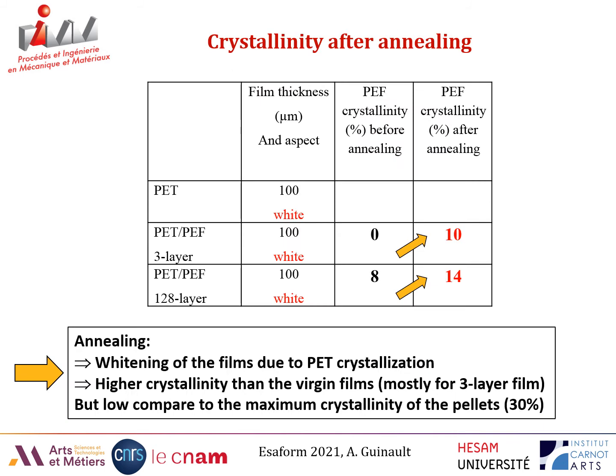So now it is interesting to see how crystallinity evolves in the 3-layer and the 128-layer film after annealing. So you can see that the crystallinity degree increased from 0 to 10% for the 3-layer film and 8 to 14% for the 128-layer film. But look, it's interesting, but you have a whitening of the film due to PET crystallization that is classical for that.